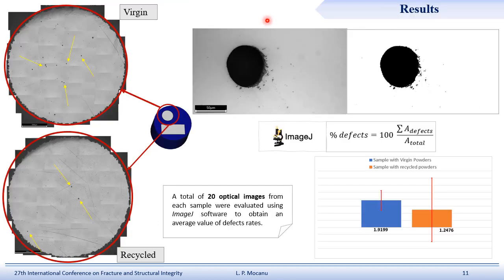Here is a more detailed view regarding the internal defects. We also performed an image quantitative analysis in order to obtain the percentage of defects, and we saw that the sample manufactured with virgin powder is characterized by a higher amount of these defects.